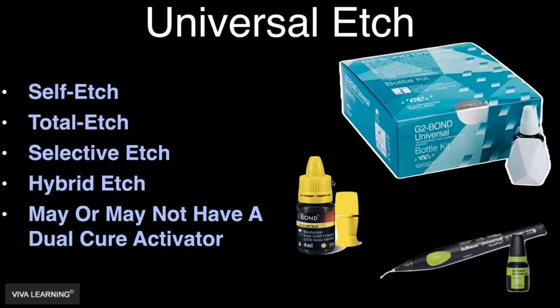So one of the things that makes it universal, because we do have to think about how the manufacturers are using that terminology, is the fact that this eighth generation, this universal generation of dentin adhesives, has a very, very unique pH. That pH is because of a very special monomer called MDP, and that pH allows us to choose any one of the four different etching techniques and use the same dentin adhesive.